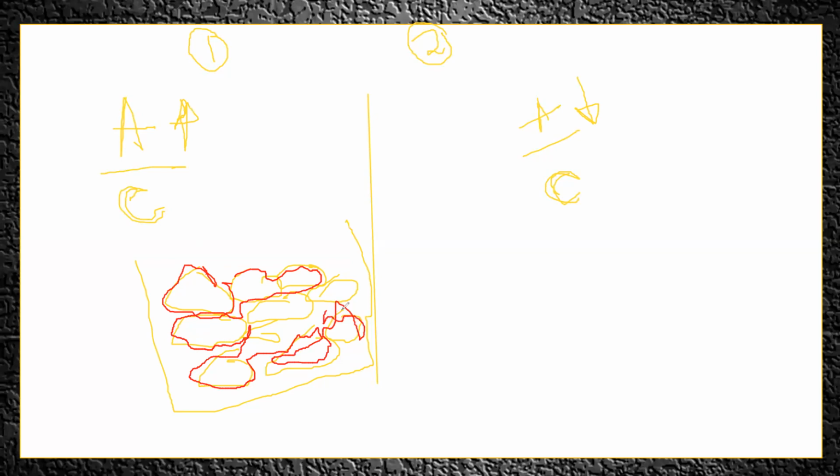First point. If more cement paste has gone in covering the surface area of the aggregate, then very little cement paste will remain for the lubrication, in the sense from the workability point of view, right? So your concrete will not be flowable. This is the meaning of the first case. Since the number of aggregates is more, the surface area is more. If the surface area is more, more cement paste is required to cover it. If all my cement paste is gone in covering the surface area, then very little cement paste is left for the lubrication, right?